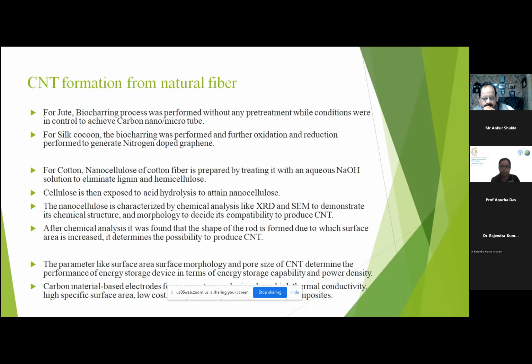That nanocellulose is characterized by chemical analysis like XRD or SEM to demonstrate its chemical structure and morphology. After the analysis, it was found that a rod-type structure is formed in which the surface area is increased. It determined the possibility to produce CNT. After producing CNT from natural fiber, we will develop an energy storage device.